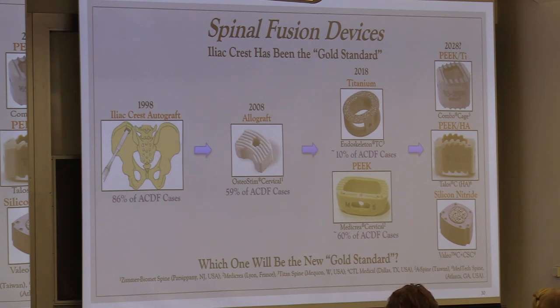The unfortunate thing about these, and particularly about PEEK, is it's basically totally inert. It doesn't interact at all. There's no biological efficacy. There is some with titanium, but not a whole lot there. So where is it going in your generation? It's either going to these composite devices, which maybe is a combination of PEEK and titanium, or PEEK and hydroxyapatite, or we hope that silicon nitride might be a material there, because silicon nitride is naturally a material which is osteogenic as well as bacteriostatic, and I'll show that here in the upcoming slides.